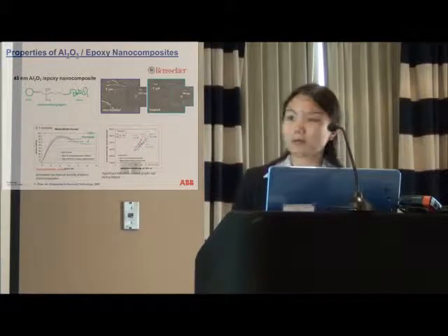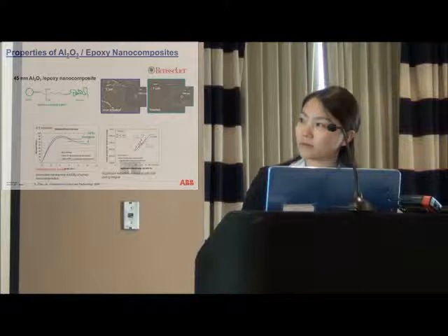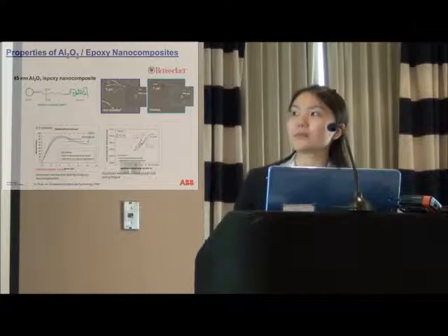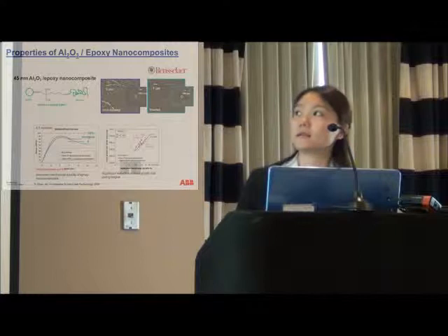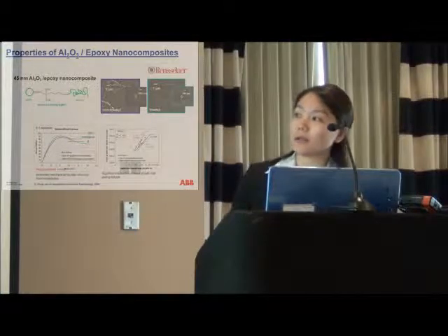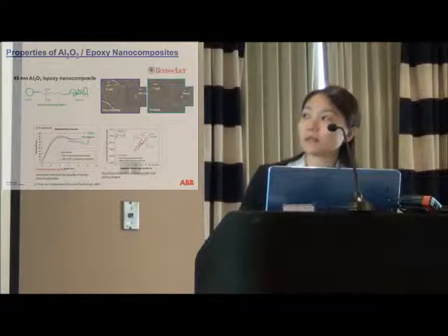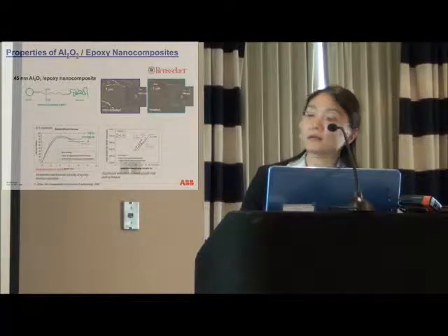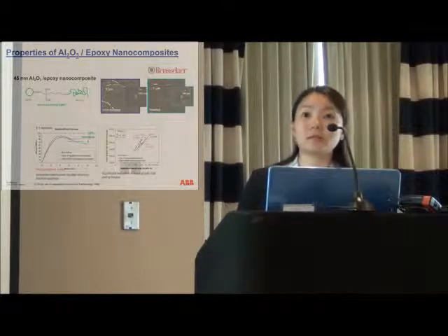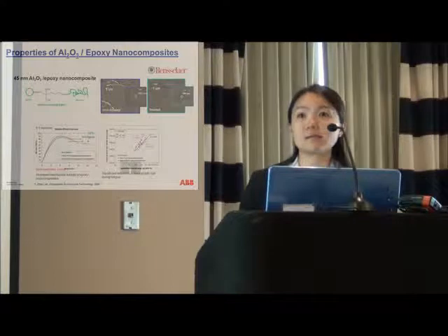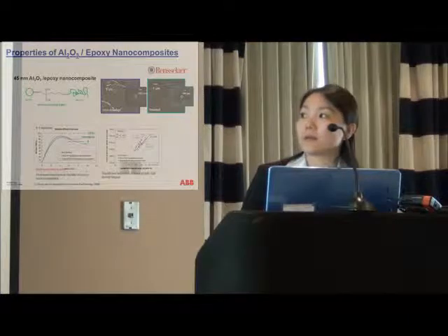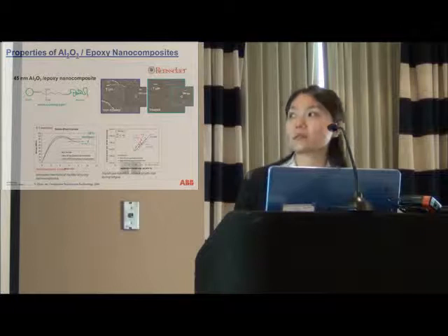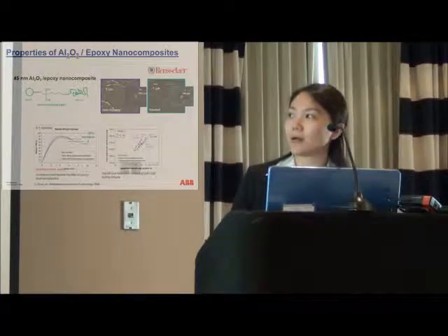So the results, on the bottom, these two curves - the left one is a representative stress strain curve. The pink one is a neat polymer, the blue one is non-treated, and the green one is a treated nanocomposite. You can clearly see that the strain to break, both of the nanocomposites improve the ductility, or you can say strain to break - this is tensile ductility. Especially for the treated nanocomposite, it was about a 39% increase compared to the neat polymer.